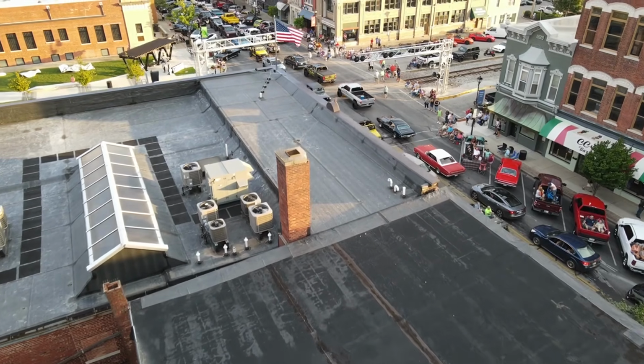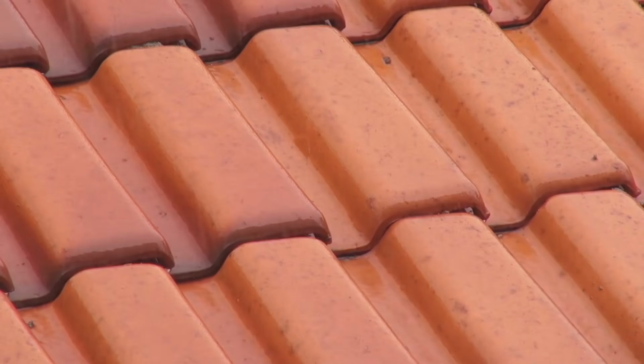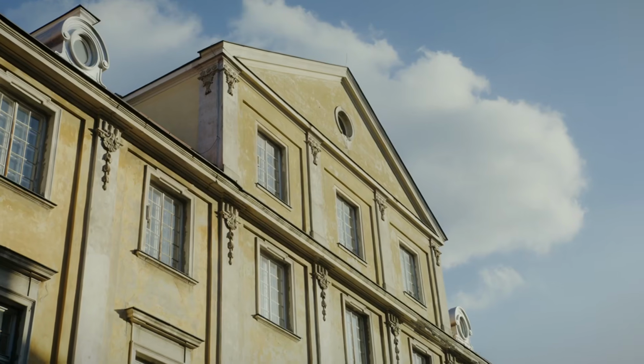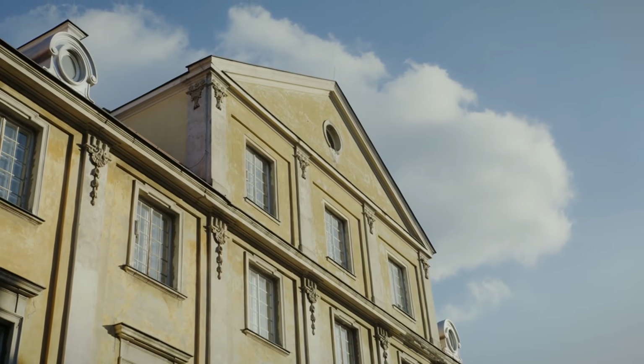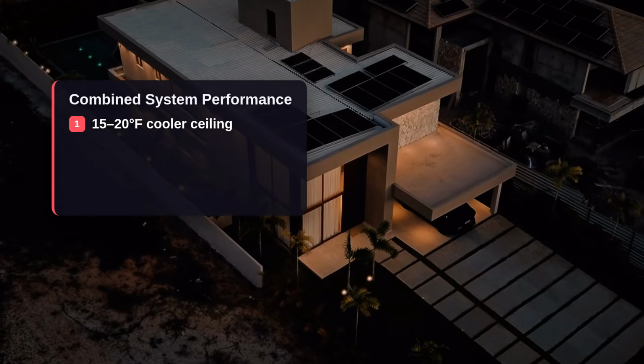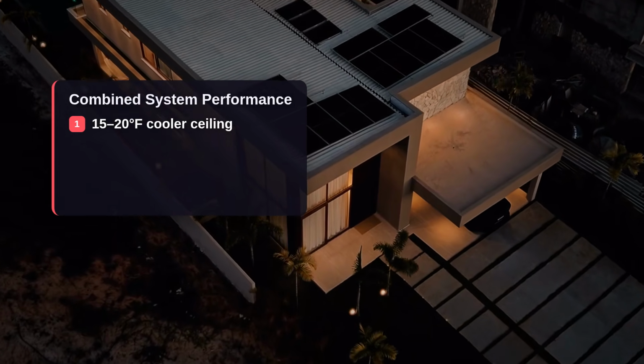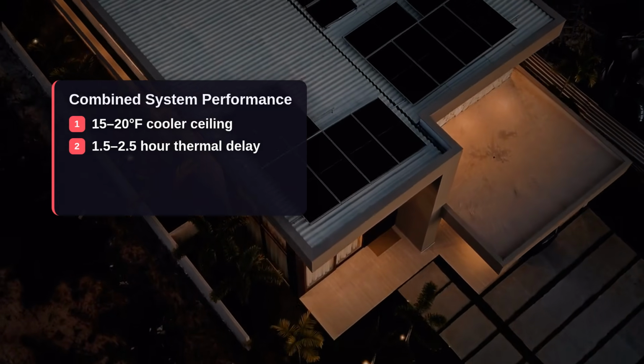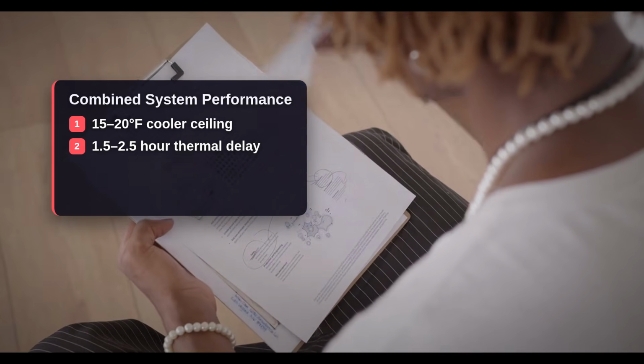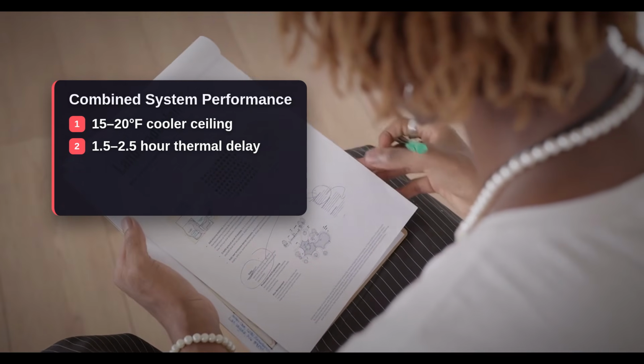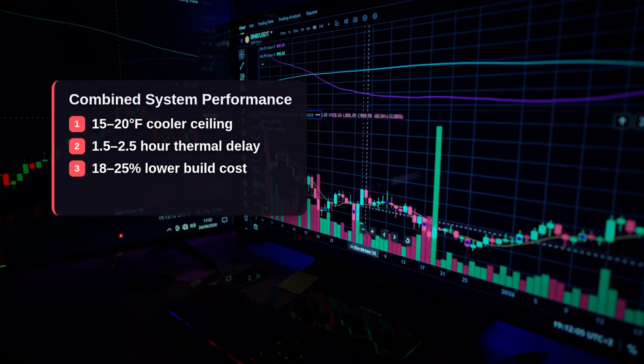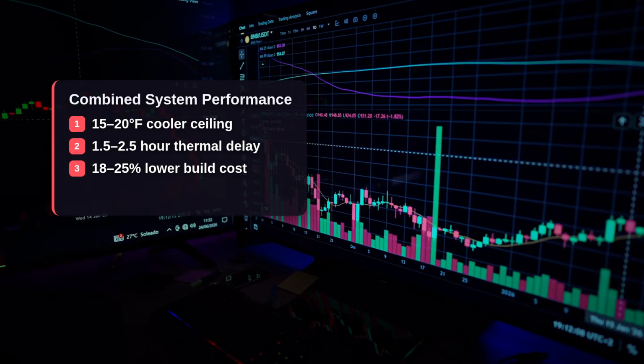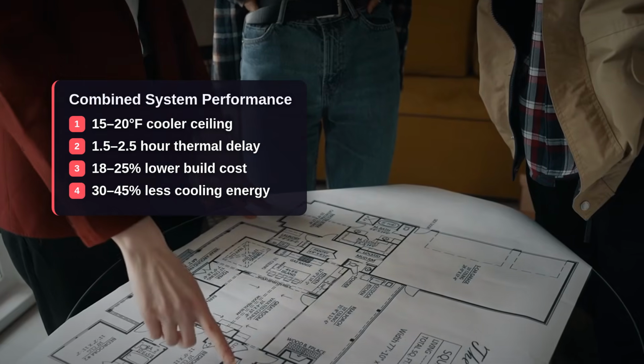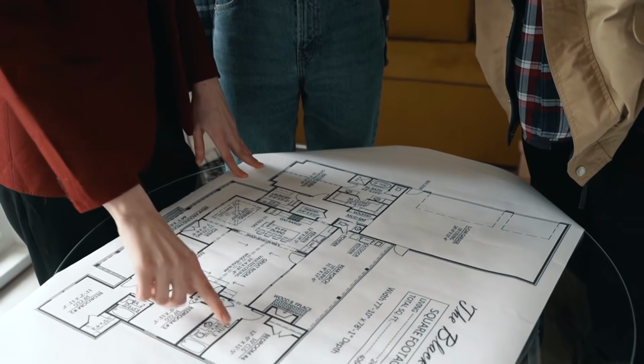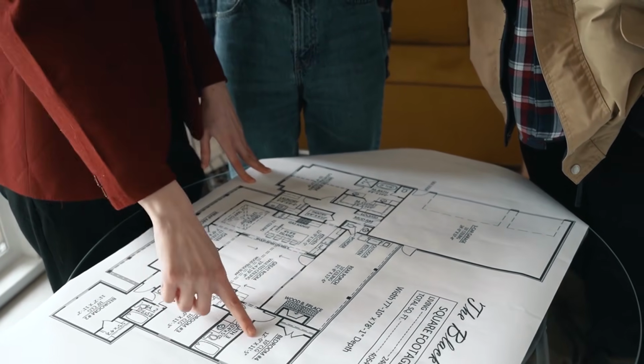Let's put the complete picture together, because the system effects compound in a way that isn't obvious until you trace them through. A correctly built clay pot filler slab roof with pre-soaked pots, correct vibration technique, sealed soffit, and reflective top surface delivers the following: a peak interior ceiling surface temperature 15 to 20 degrees Fahrenheit lower than a conventional slab. A thermal peak delay of 1.5 to 2.5 hours, shifting the maximum interior heat load from mid-evening to late night. A construction cost reduction of 18 to 25% versus a comparable solid slab, and a 30 to 45% reduction in mechanical cooling energy over a full summer season. These aren't independent benefits. They stack.